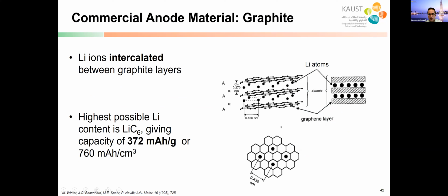So graphite as anode material, graphite is a layered structure, basically looks like this. And then what happens is that lithium ions, during the charge process, come into the layers of the graphite. The word intercalated or intercalation means that the atoms can go into this host structure without destroying it. Basically, they may cause a small strain, about 7 or 10%, but they don't destroy the structure. They go in and they come out. And then the capacity, remember I told you energy density is related to capacity, for lithium intercalation into graphite, about 372 milliamp hour per gram.